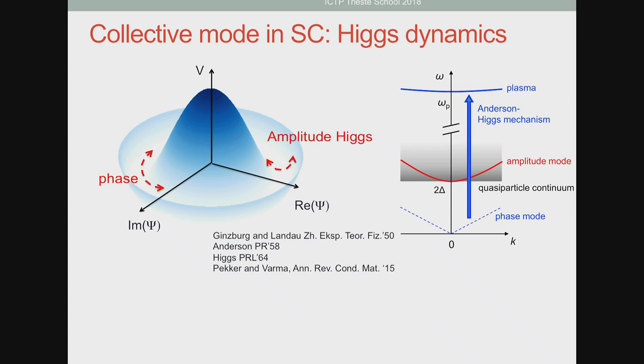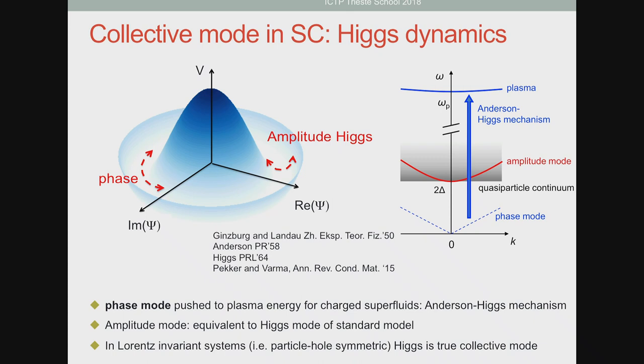Now, this has been worked out actually in the 60s by various people, and what you can show is that if the superfluid is neutral, let's say, for example, like helium superfluid, the phase mode is linearly dispersing as a function of momentum, and the amplitude mode is gapped, and it's gapped by an amount which is twice the superconducting gap. Now, if you are in a charged system, actually the phase mode couples to the Coulomb interaction and is pushed to the plasma energy. This is the so-called Anderson-Higgs mechanism, so it's essentially irrelevant in superconductors. It's just the plasma frequency.